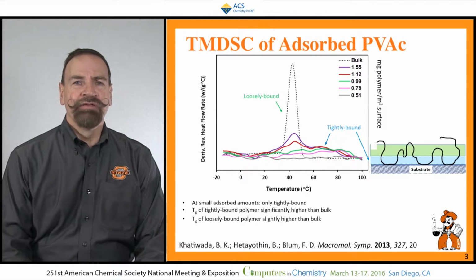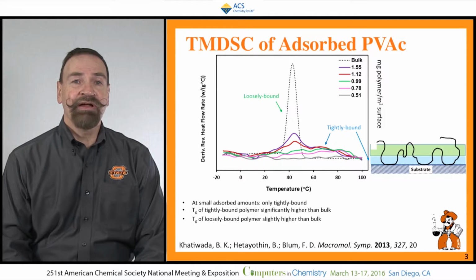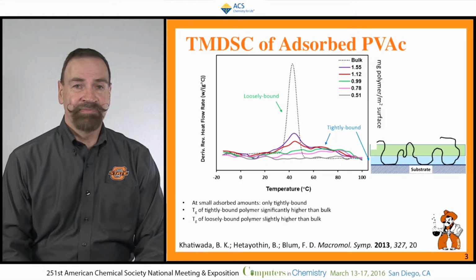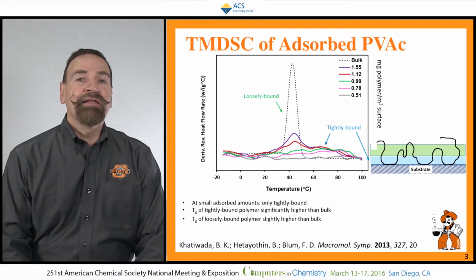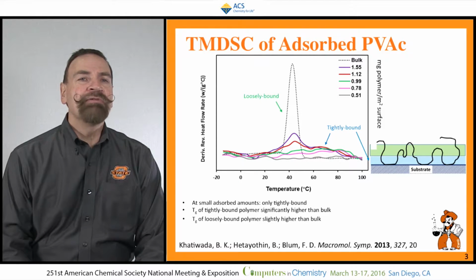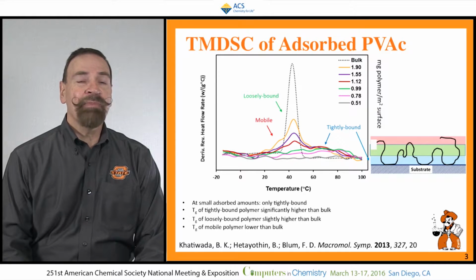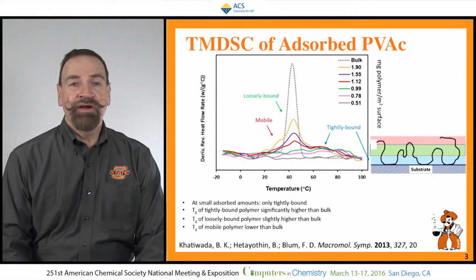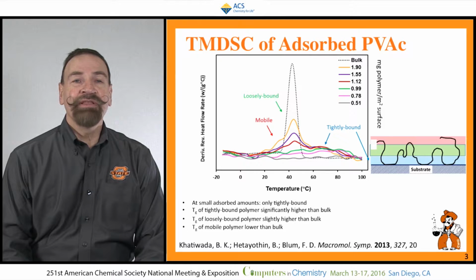That's what we call loosely bound polymer. And this loosely bound polymer has behavior that's similar to the bulk polymer. This loosely bound polymer is what I would show in the green region here. As I add more polymer, now I see that there are polymers that behave like they're in the red region.